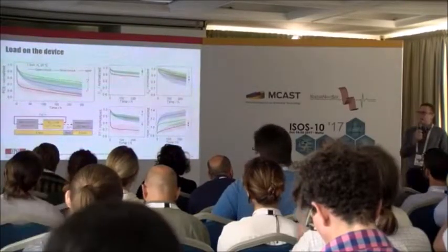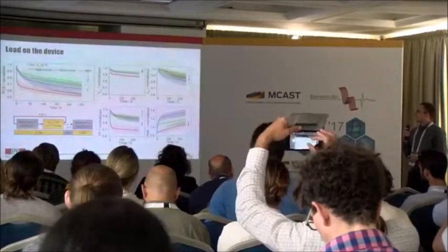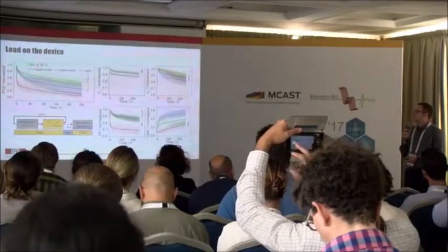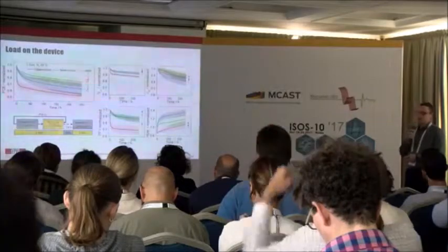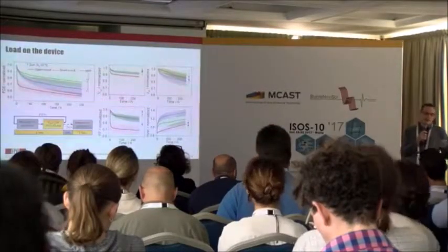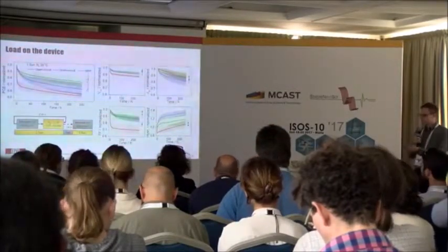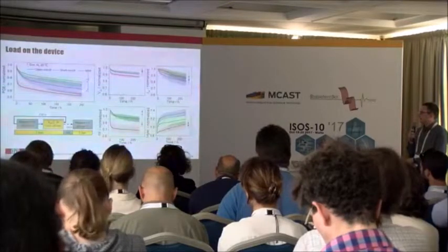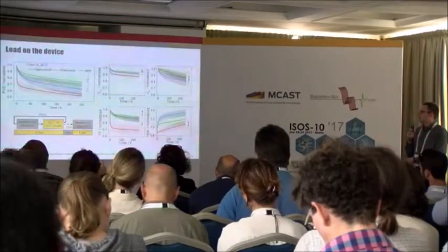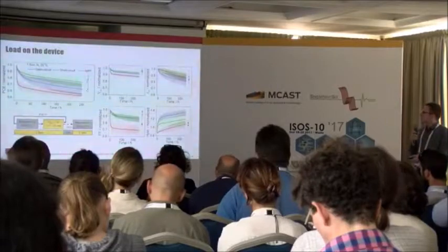to the observed degradation. And by the way, I should have started by saying how we did the experiment. We kept those devices under open circuit, short circuit, or MPP, and we periodically measured JV curves. So this is the procedure here. We let them recover for 24 hours.